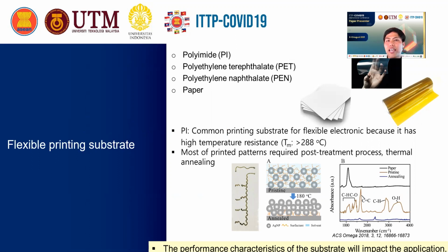Look at PEN or PET, they are low temperature stable polymers. When we apply heat, they will melt, maybe at 150 degrees, or show a shrinking surface. But coming back to high temperature polymers, why do we need a high temperature curable printing substrate?